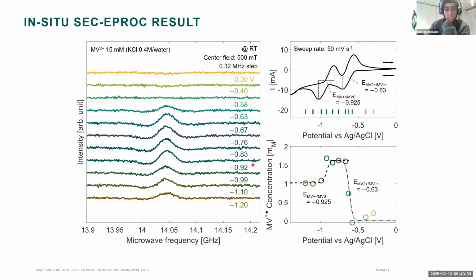So again, similarly to what I've showed you before, he applied a series of different potentials and then measured their EPR intensity. And again, similar to my previous examples, the potentials that you get from plotting the EPR intensity against the potential match very nicely with what we determine in the electrochemistry. So we have direct and accurate potential control over our system. The sensitivity in the in situ SEC-EPROC was able to go down to about 250 micromolar, but there are further improvements currently ongoing to lower this.